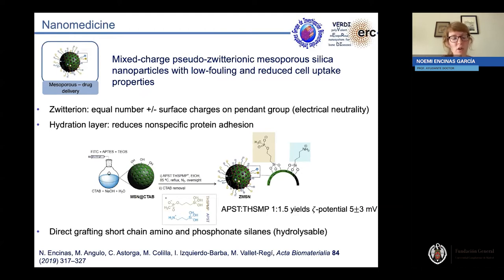So what we tried to do in this work that I ran with Dr. Montserrat Colilla and Isabel Izquierdo was to create, let's say, a nanocarrier that was able to somehow avoid this type of internalization. Knowing that a zwitterion is defined as a distribution of groups with an equal number of positive and negative surface charges on pendant groups that basically promotes a certain electrical neutrality, and it creates a hydration layer that somehow reduces the non-specific protein adhesion, we wanted to modify the traditional mesoporous silica nanoparticles with this type of groups.